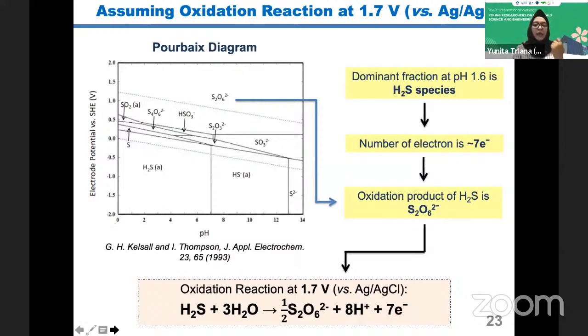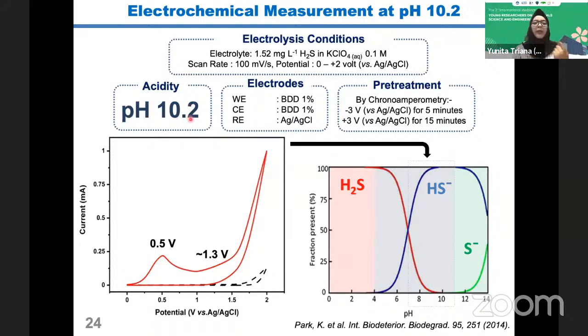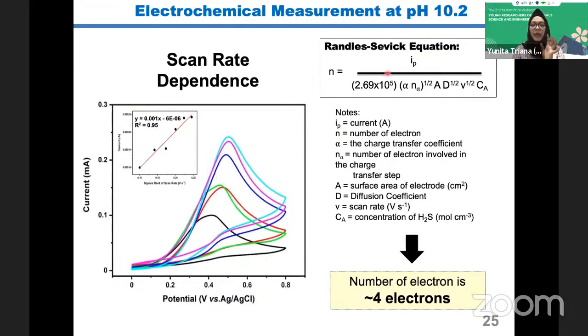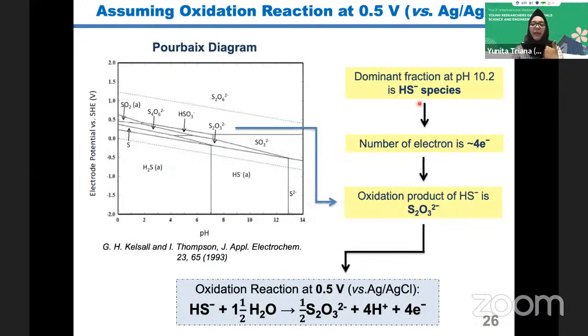And also I tried a high pH, 10.2. At pH 10.2, I got two potentials. At pH 7, I got three, right? 0.5, 1.3, and 1.7. At pH 1.6, I just got 1.7. But at pH 10, I got two: 0.5 and 1.3. Based on this graph, at pH 10.2 there is one species, HS minus. Then I also did scan rate dependence, and at pH 10.2, via this equation, I got 4 electrons. So the dominant species at pH 10.2 is HS minus, and the number of electrons is 4.